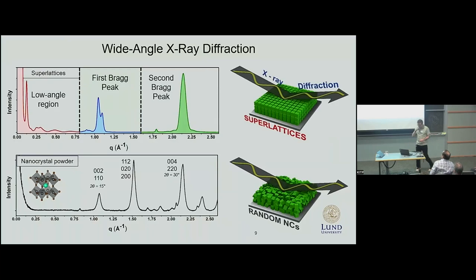When we repeated this on one of these superlattice samples, whether film or isolated, we saw a very different pattern. In the low angle region, peaks as expected from the superstructure. Then we lost some of the reflections due to preferential orientation. And the first Bragg peak, moreover, showed a peculiar fine structure.